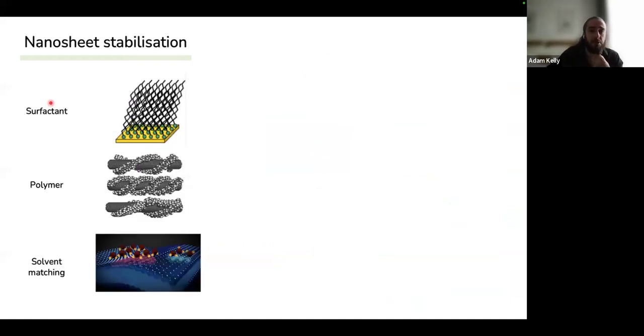So stabilizing your material within dispersion can be done by surfactant, where we have these chains which will bond to the surface of the nanosheet, to the basal plane, and then you will have electrostatic repulsion preventing them from reaggregating inside a dispersion. Another way to do it is by polymer adsorption, where we add in a polymer to our dispersion, and this will adsorb on top of the material, and we'll have steric repulsion, preventing the nanosheets from coming into contact and reaggregating. Another way to do it then is also by solvent matching.